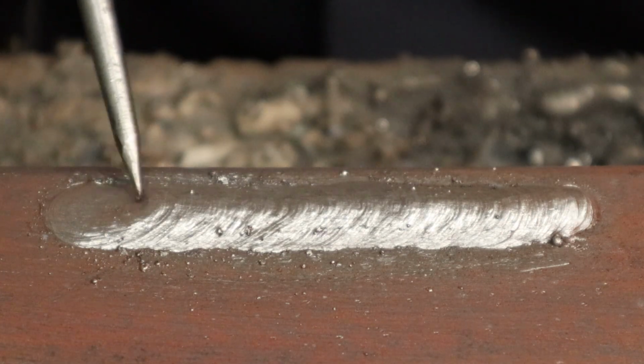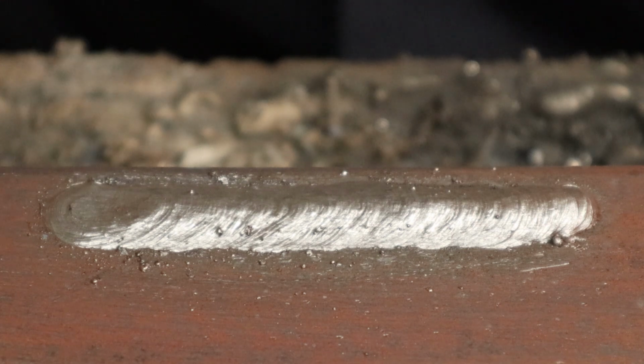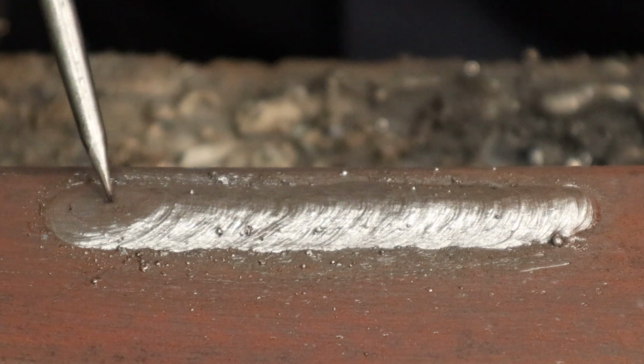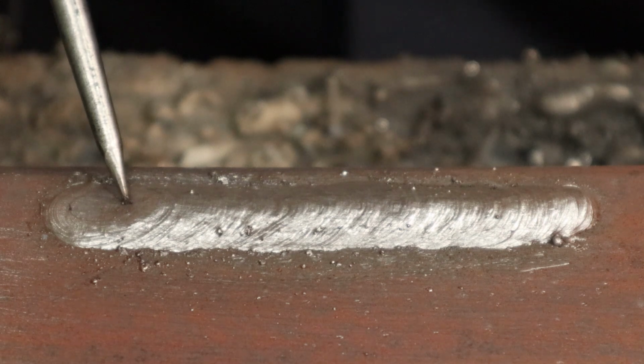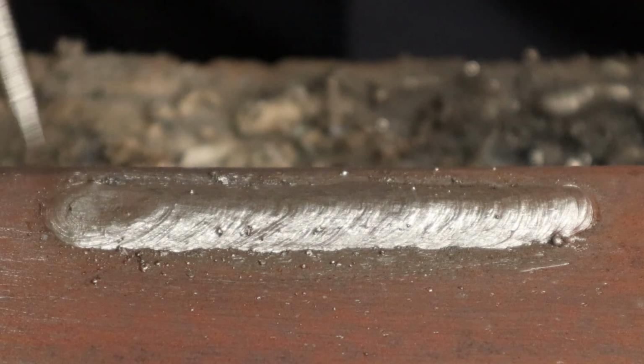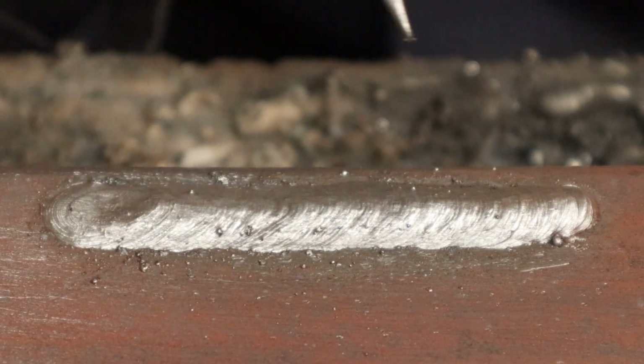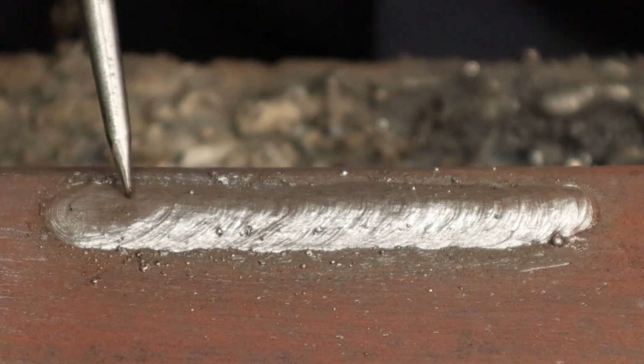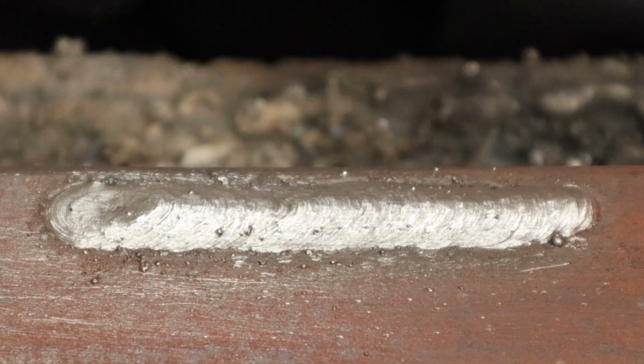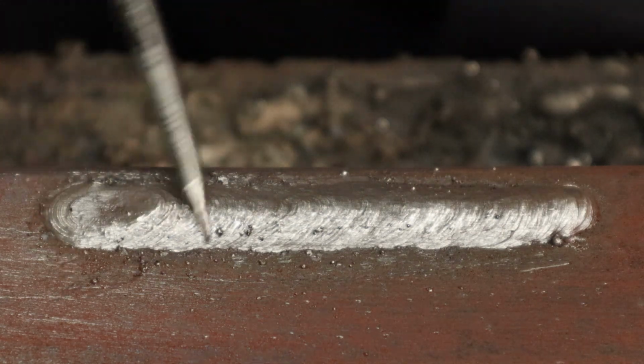And at the end, there isn't a huge crater where I just pulled off and didn't have enough material. So I paused for a sec, got some heat, put some material in. And there is no arc burn lines because when I pulled it away, I went up over my previous weld where the slag is. So not my greatest weld, but not bad for today's lesson here.